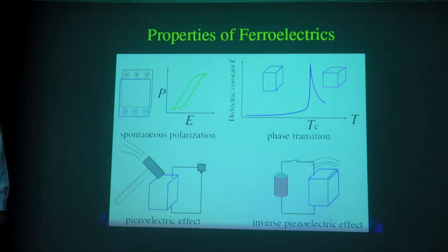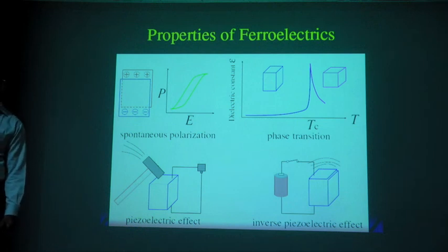And what my work has shown recently is that the phonon zero point motion stabilizes the other ground state actually, and that's how it has shape memory. So soft phonons are very important. They can easily give you a different ordering of stability of different phases.